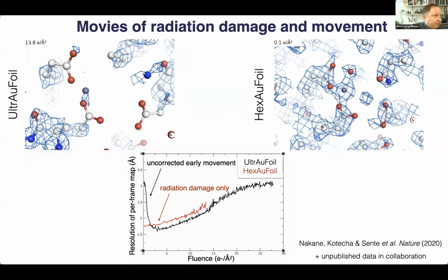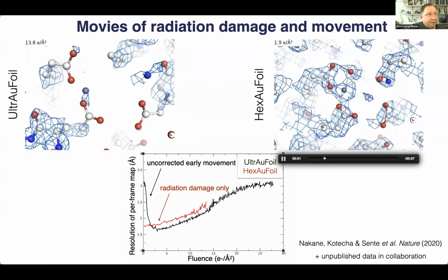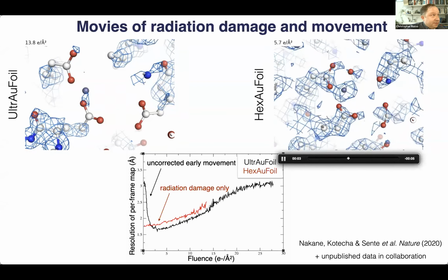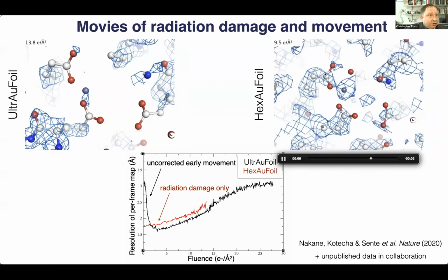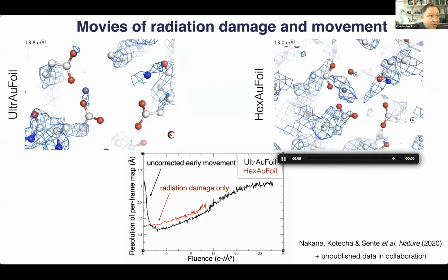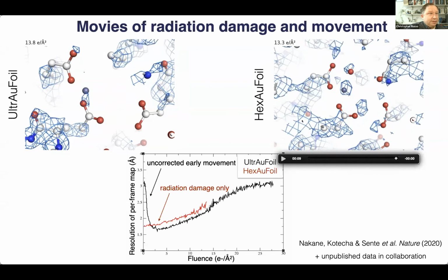That's what's characterized here. So if we look at the same thing on one of these hexafoil supports where the movement is eliminated, you find that the first electron per angstrom squared is the best still. And you can see that in all the little features in the map, the water molecules, the side chains, the ions, and it gets progressively worse. So, you end up with a curve that looks like this. So, having a high resolution map is not a solution to radiation damage. It does give you more features in the map, but they may not necessarily be features of an undamaged molecule.